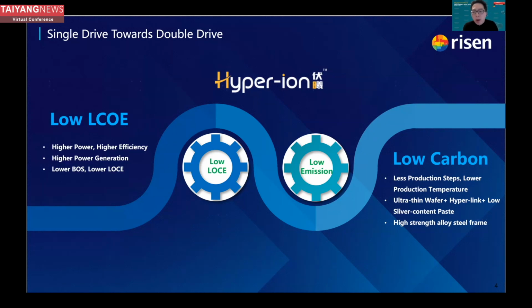target, which is lowering the LCOE and also the carbon emission, because heterojunction has a higher power output, high efficiency, a higher bifacial factor, a better temperature coefficient and low degradation, which helps us obtain a higher generation yield. And because of the geometric structure and the low-temperature production procedures, we can also reduce a lot of the carbon emission. Along with thinning of the silicon wafer, we can also reduce a lot of raw material consumption.